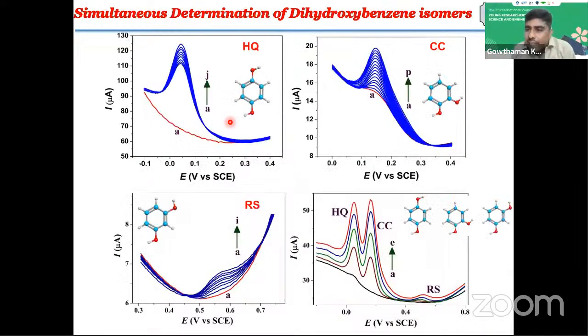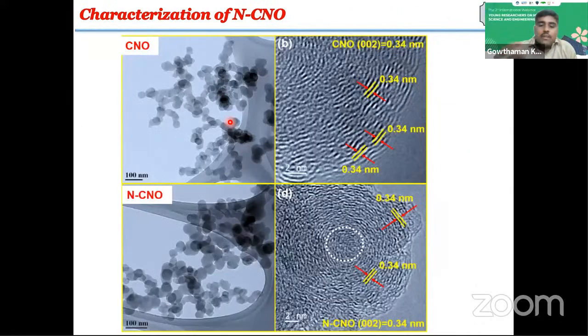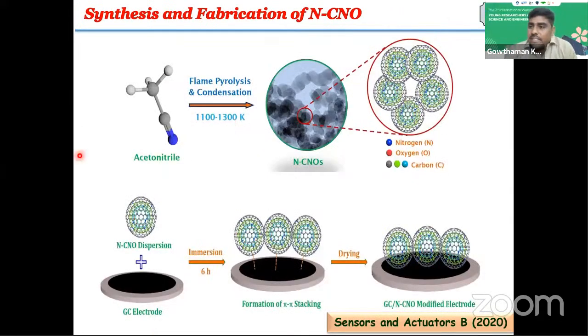Okay, so the material was used to fabricate the electrode. Actually, I forgot to inform. For the electrode fabrication here, there is no electric current, there is no electrolytic deposition. We just immerse the electrode into the solution containing the carbon nano onions. Pi-pi stacking and electrostatic interaction lead to the formation of carbon nano onions on the electrode surface without any linker. There is no linker, only the electrode immersed into the solution. There is a formation of carbon nano onions on the electrode surface.